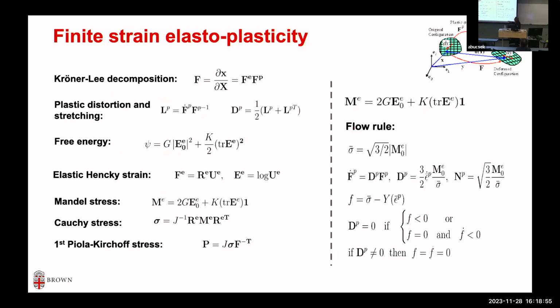So in order to do the large deformation plasticity problem, the elastic plastic material is isotropic, with rate independent hardening. This is the conventional plasticity framework for that. Elasticity, again, is a three-dimensional tensor, and for plasticity, this is the yield function. So it's rate independent plasticity. I will not go into details, but it's basically the finite deformation plasticity framework.